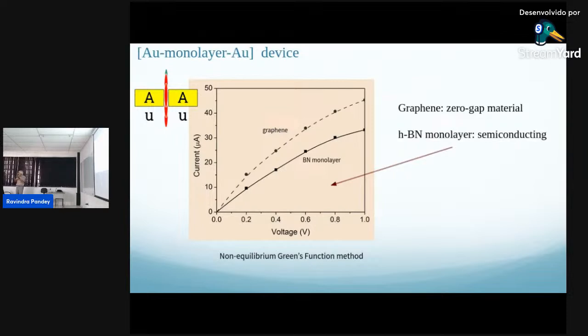So let's start with the monolayer. We have either a graphene or a boron nitride single monolayer, and we look at the current versus voltage. Now, graphene is a zero-gap material, so we expect ohmic-like conduction. That makes sense. Boron nitride is a semiconductor, so our expectation is diode-like behavior: flat and then taking up. This is not the case here. It just behaves like a metal with ohmic current.